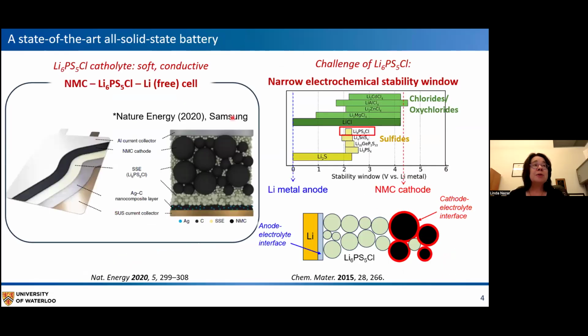So here's an example of a state-of-the-art all-solid-state battery of Samsung's. It uses a nickel manganese cobalt cathode, a conventional cathode, and argyrodite as the electrolyte. And this is a lithium-free cell, so this is resembling that anode-free cell in the previous slide, except what Samsung has done is taken a silver carbon composite layer here to achieve their anode-free configuration.